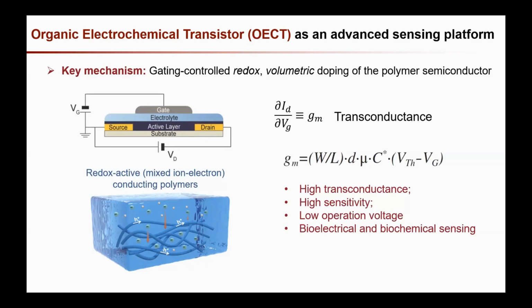So this is enabled by the semiconducting polymer to have not only semiconducting property, but also can allow the transport of ions into the entire bulk volume. So then what's the benefit? The benefit is that when this type of transistor is working as an amplifying or sensor device, this volumetric gating mechanism can greatly benefit to have a much larger capacitance of the gating.